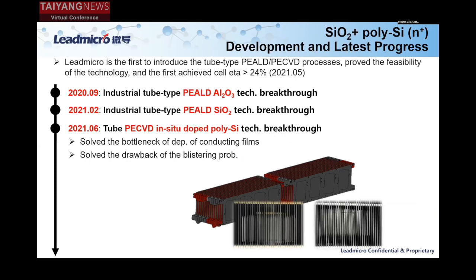For the equipment issue, everyone is probably quite familiar with the tube type PEALD or PECVD system. In the past, we used this PECVD system to deposit mainly insulating films, like silicon oxide, silicon nitride, and silicon oxynitride. This is the first time we are using this tube PECVD system to deposit a conducting film. So why is the conducting film very challenging? We use this graphite boat as an example. You can see the graphite boat here in the left graph. The neighboring two plates have to be separated by the yellow insulating ceramic rings. Why do they have to be separated? Because the two plates have to conduct the AC current to generate the plasma. However, when you deposit the conducting film, as you can see in the right image in silver color, if the insulating ring becomes conductive, your neighboring two plates will be joined together.